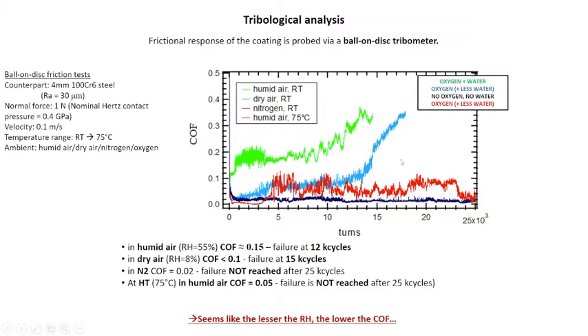These first results clearly show that even if we do not have the presence of the columnar structure, we still have a very important performance of MoS2, which is able to support lubrication. So from this experiment, we can support the thesis of Spalvins related to the sliding model.